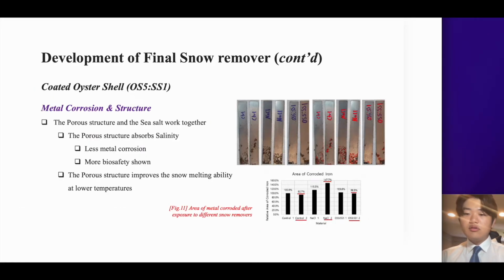In terms of the metal corrosion characteristics, it was first expected that the corrosion would increase since the oyster shells are mixed with salt. However, as can be seen from Figure 11, which shows a comparison of metal corrosion characteristics, it is inferred that the porous structure of oyster shells inhibited corrosion, and oyster shells show similar corrosion characteristics to those of the control sample. As a result, I concluded that the porous structure and sea salt match well, complementing each other.